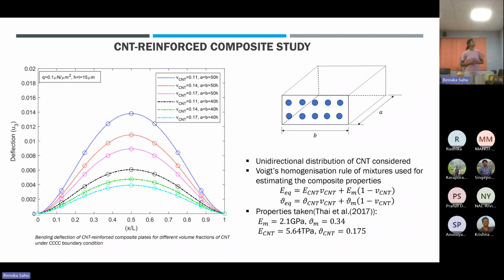We have considered three different volume fractions, wherein the plate thickness and material length scale parameter are kept the same for all cases. We can clearly see that for a smaller plate width to thickness ratio, you get a smaller deflection, which is again smaller for a higher CNT volume fraction compared to a lower one. And if you go to A equals B equals 50H, you get a higher deflection. So that is done here.